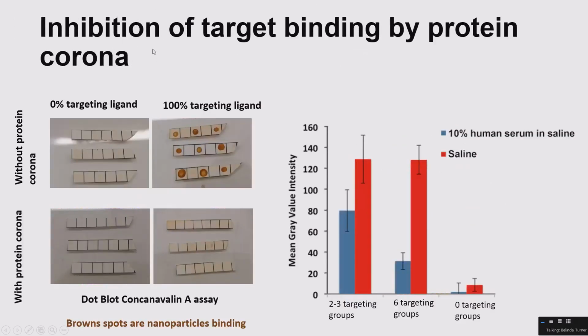So then we did a bit of work as well looking further into this inhibition of target binding by the protein corona. So here we've got these strips of paper, and this is called a dot blot assay. This row here is nanoparticles without a protein corona, so just binding on their own. We've got 0% targeting ligand on this left side and 100% targeting ligand here. The nanoparticles are brown. So with 100% and no protein corona, there is a nice, very clear binding. But then once we introduce the protein corona, you can see there's virtually nothing there. So there is an inhibition of binding being caused by the proteins in this mixture.